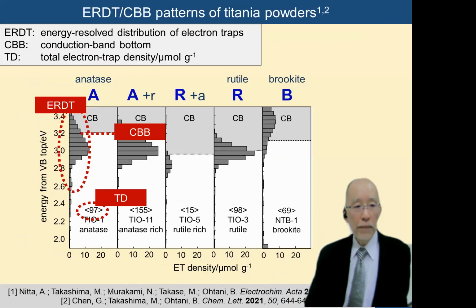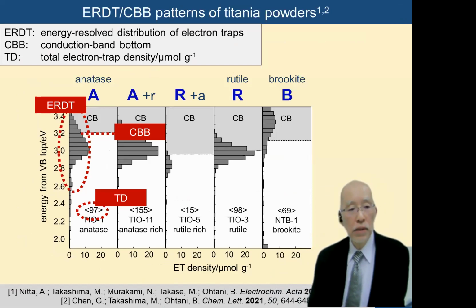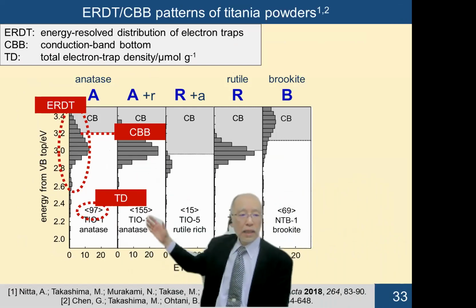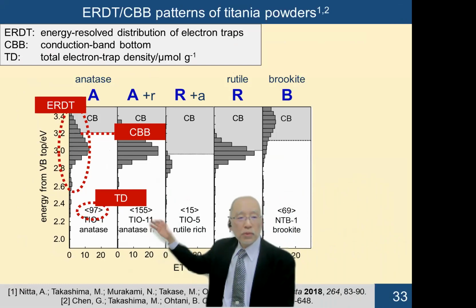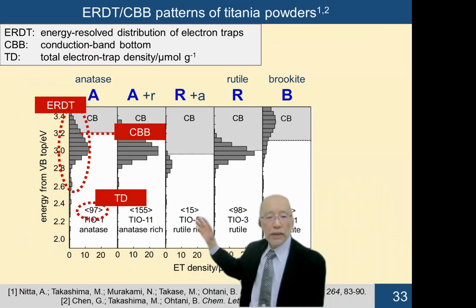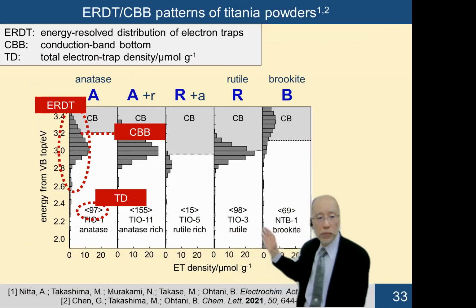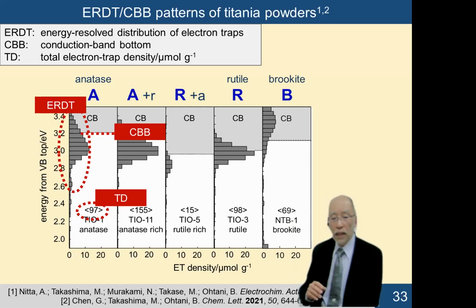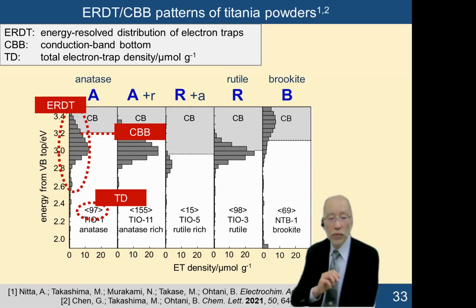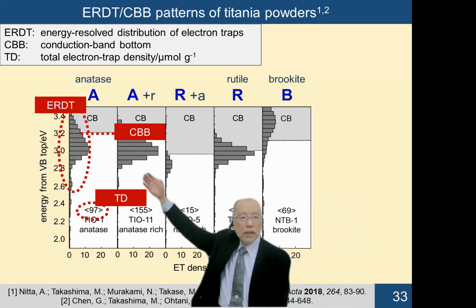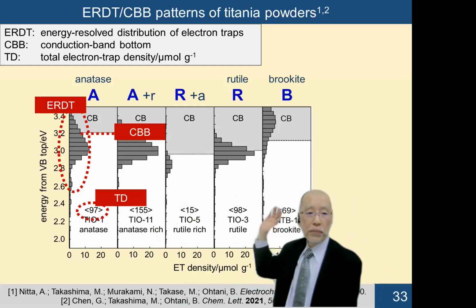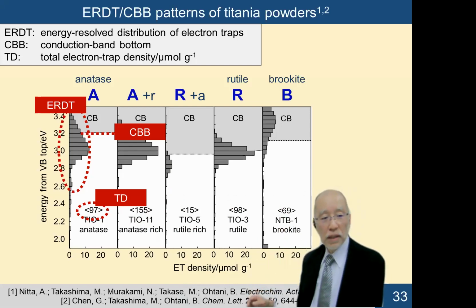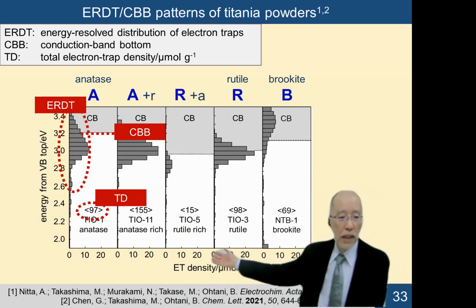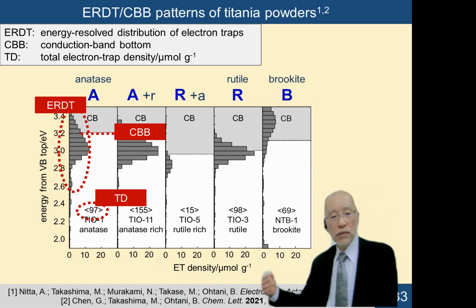Okay, this is the results of ERDT-CBB pattern analysis for commercial titanium oxide samples. And anatase sample, that is shown A, and anatase-rich with a small amount of rutile, A plus small r, and the rutile-rich R plus small a, and rutile titanium oxide and brookite. But that is just determined by XRD. And we have no information about the non-crystalline part that might be included in those materials. And you can see the ERDT pattern and the CBB position and the TD for those samples. Yes. And probably you can see the difference of ERDT-CBB pattern depends on this crystalline structure. Probably that is almost okay.